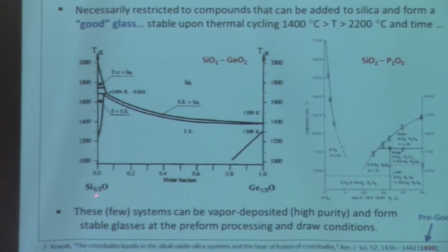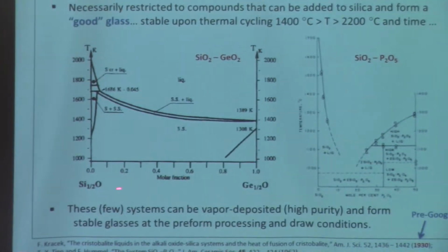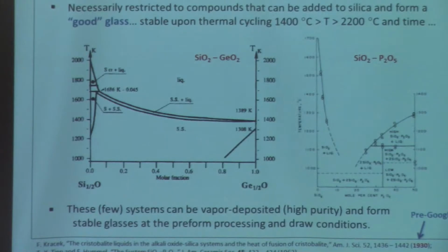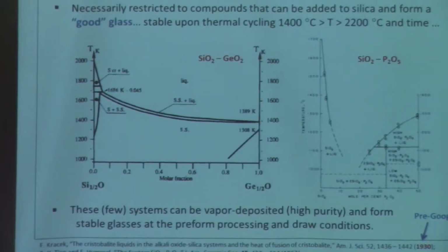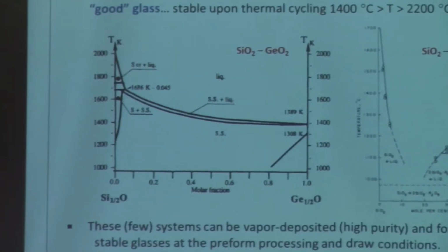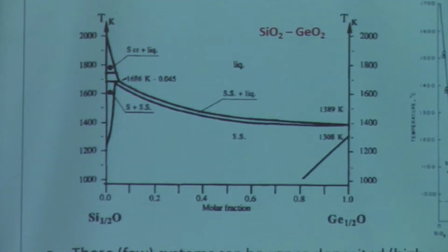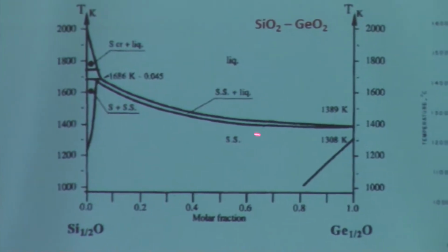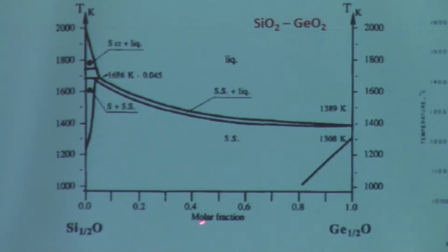This is what's called a phase diagram. So this is SiO2, GeO2. In this system, there's complete solubility. So you can mix as much or as little SiO2 with GeO2, no water and oil. Beautifully mixed, okay? And you'll see there's a liquid. This line defines for you, at any given combination of those two, the temperature at which that combination melts. So it's a solid down here, it's a liquid up here. Keep that in mind. So for germania, for phosphorus, right?